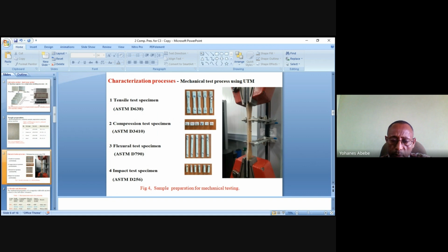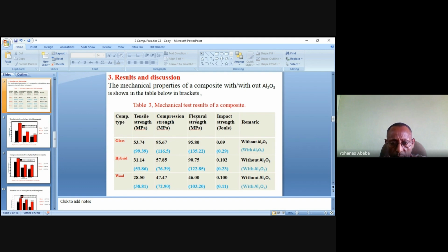When it comes to the characterization process, once I prepared the samples based on the standards, I used the UTM, universal testing machine, in order to check the mechanical properties of the composites. The mechanical properties include tensile, compression, flexural, and impact tests, including water absorption. When we come to the results and discussion part, this table shows the glass fiber, the hybrid, and the wool fiber composites. These composites were tested with 2% nano, without the application of nano-alumina, and with the addition of nano.